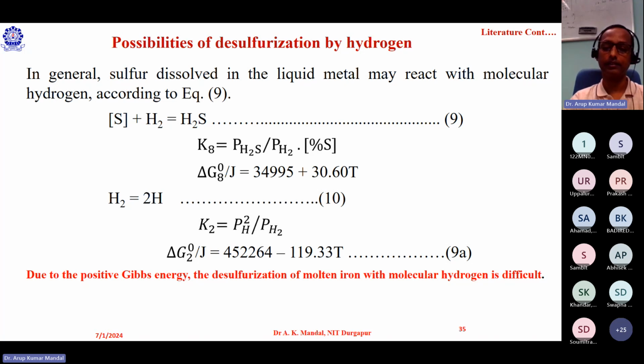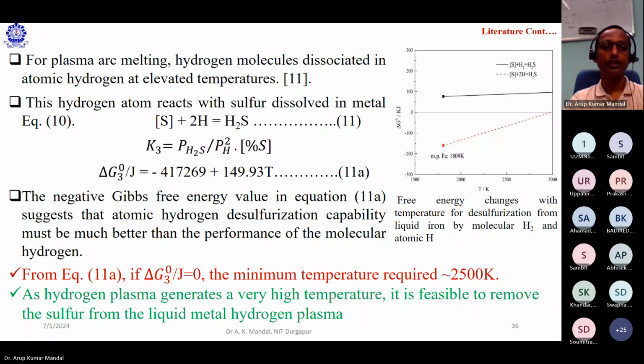To make it possible, what can we do? If you see this equation, the sulfur dissolved in the liquid metal reacting with hydrogen ions, you can see the minimum temperature required for this feasible reaction is about 2500 Kelvin. It means if you can increase the temperature to a certain level, then the hydrogen in the ionic state can react with the dissolved sulfur.